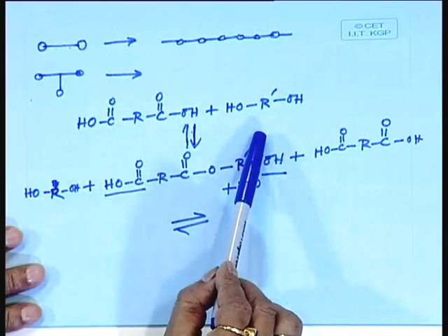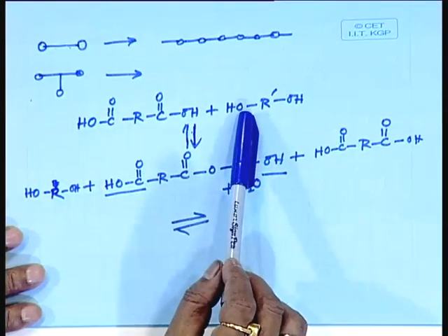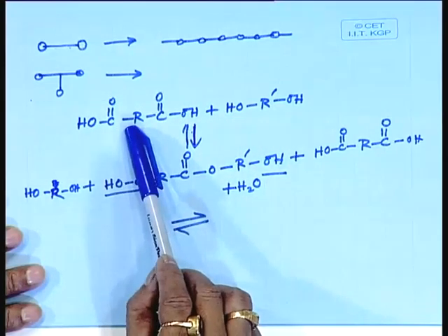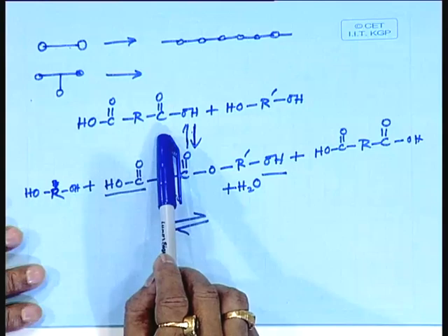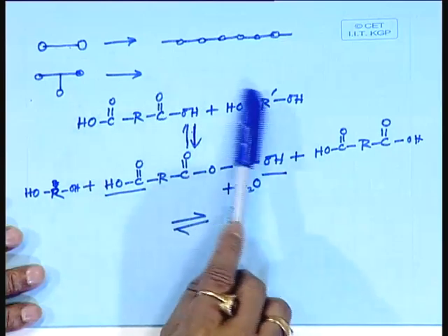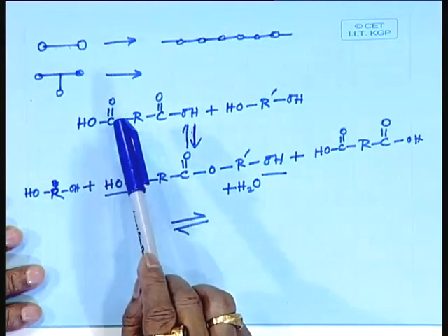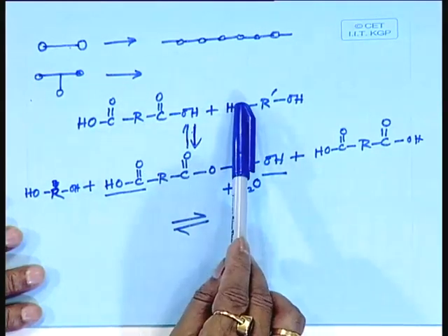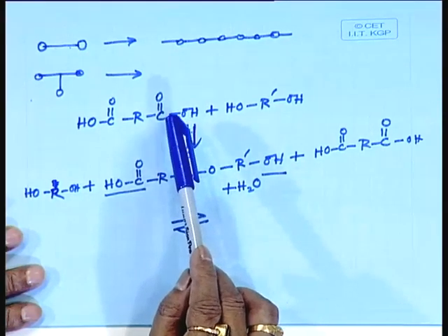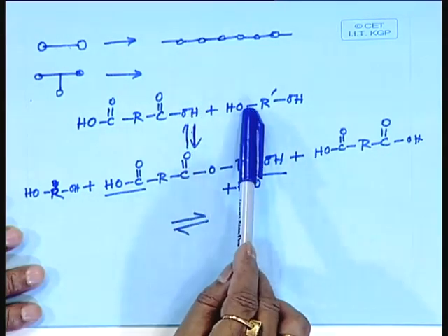These are chemical compounds. So, you have to know the purity level of these things. If they are not 100% pure, then the amount you are weighing, can it be 1 mole exactly? No. So, there is something wrong, wrong amounts you are taking. So, there is no strict control of the mole ratio of these two reactants. This ratio is called stoichiometric ratio, stoichiometry between the reactants. This is a problem in condensation polymerization.